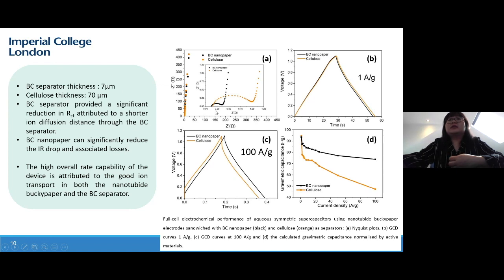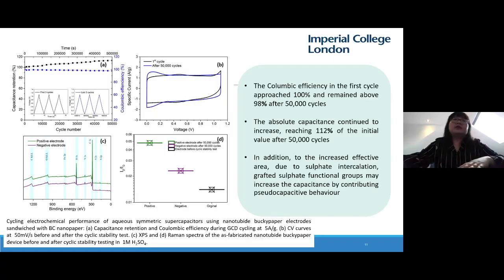And the charge transfer resistance actually drops a lot compared with the cellulose separator, due to the lower thickness, about 10 times thinner. That means the BC nano paper can reduce the resistive loss and also improve the power density. To further study the cycle life of the device using the BC nano papers, I fabricated it and